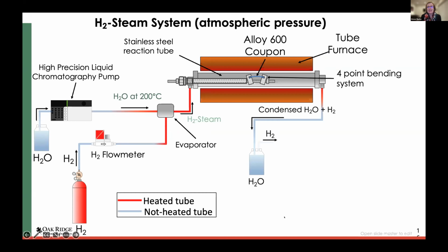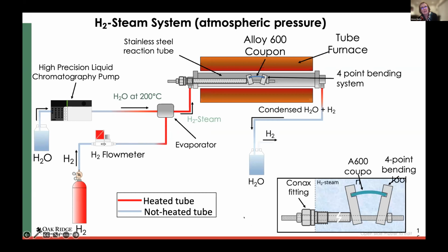Now we're going to test this, and this is done in a very simple system. My colleague Fabio Scenini and two of our students, Giacomo Bertali and Liberato Volpe, had modified and improved it. I had attempted this back in 1978 and I wasn't successful, so I'm very pleased with this. Anyway, hydrogenated steam, very simple. We bubble water through, we superheat the steam, and we've got hydrogen here, we mix it, and it just flows through this reaction tube, comes out, goes into the water. Very simple, atmospheric pressure. But to look at the effect of stress and strain, we've got a 4-point bend coupon in here too. Again, the result of some lovely work by Liberato Volpe.